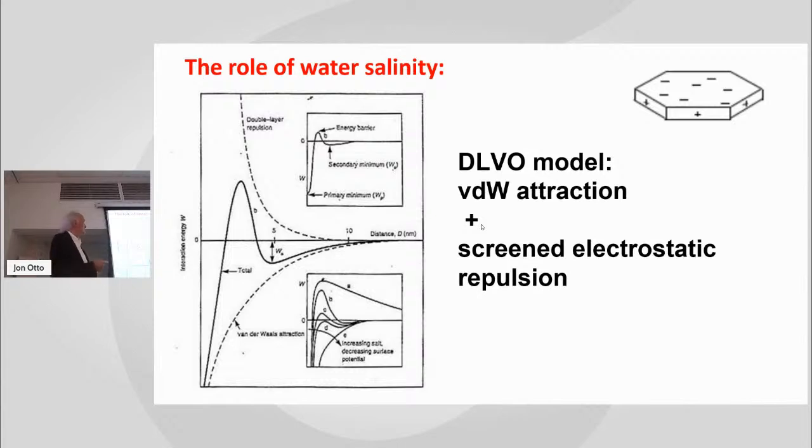But if there is no salt in the water, if it is pure water without any salt, that attraction will be dominated by the electrostatic repulsion, so that the platelets will be repelled from one another. What stops them from going to infinity is the container. If you have a container and a given concentration, that gives a distance between the platelets in the suspension.